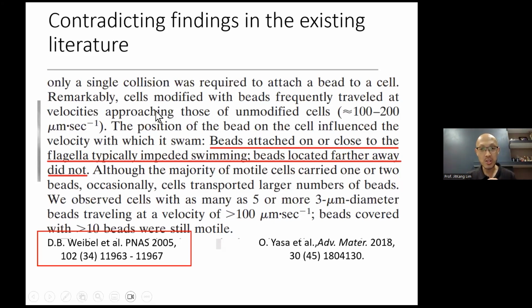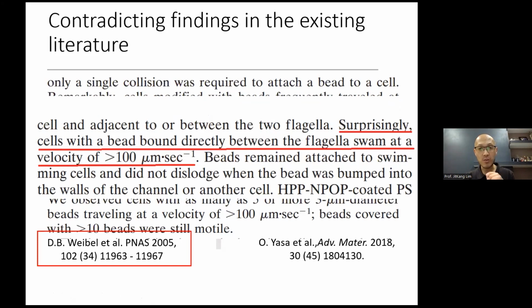So this is non-surprise. However, they observe a very surprising result. They say, when a cell with a bead bound directly between the flagella swam at a velocity of more than 100 micrometer per second. Surprisingly, when the beads are actually at the center and fixed at the center and suppress the flagella, the microbot actually can swim much further. So this, and this group is a very famous group. So eventually they motivate us to further pursue what is actually happening in between, right?